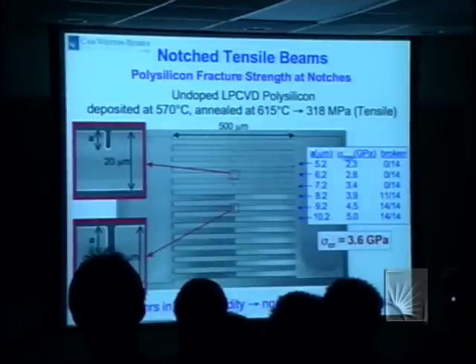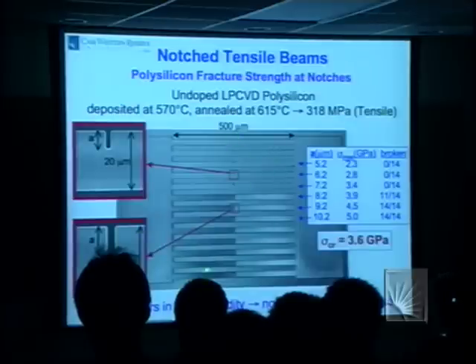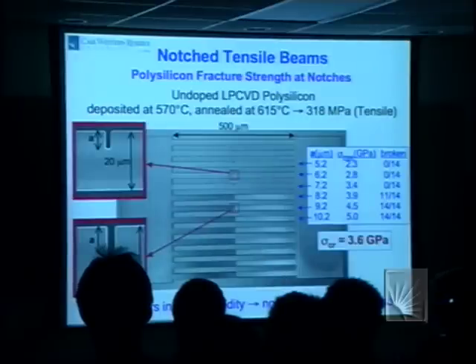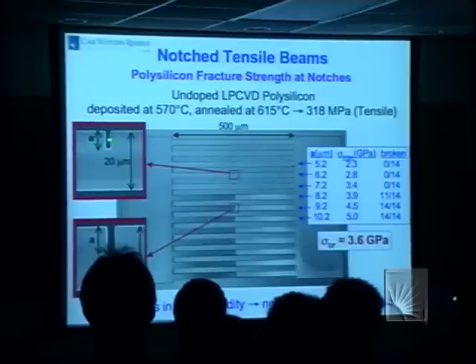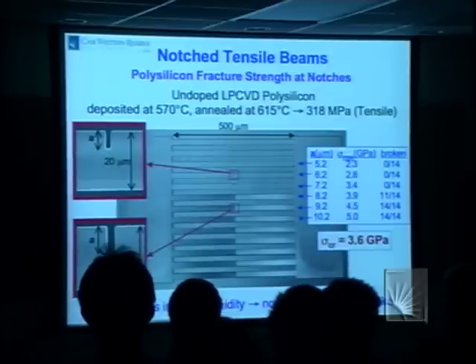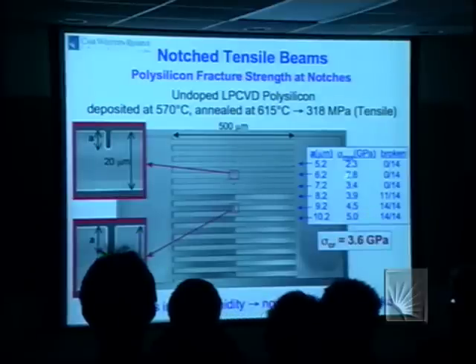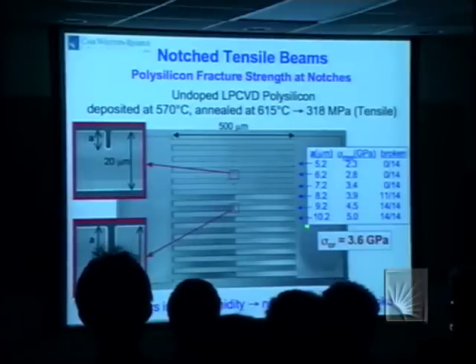And here's the device. So this is one beam, this is a second beam, and so on. This was a sample that had 318 megapascal tension as measured by our strain gauge. At this notch depth, the stress concentration at the root of the notch was too small to cause fracture. This one, it was large enough. And you can see these are our statistics. These are our notch depths. These are the calculated stresses. And this is the statistics.